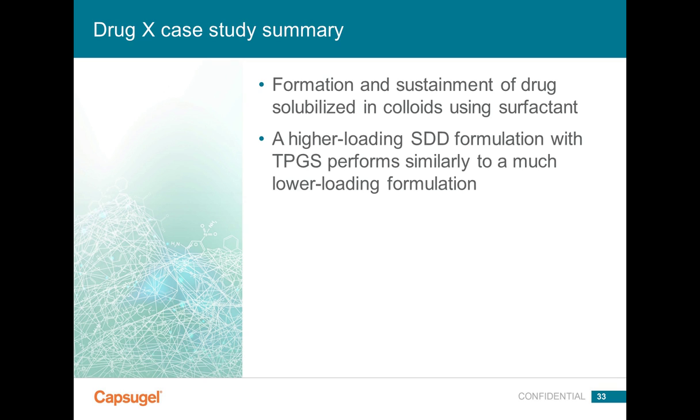To briefly summarize this case study, the formation and sustainment of drugs solubilized in colloids is done using surfactant. A higher loading SDD formulation with TPGS is going to perform similarly to a much lower loading formulation without it. That means that TPGS inclusion is a really helpful way to enable us to increase the loading in the formulation, which is often of very high priority.